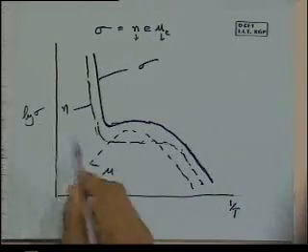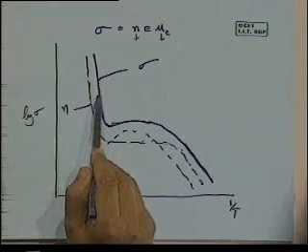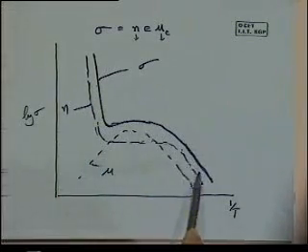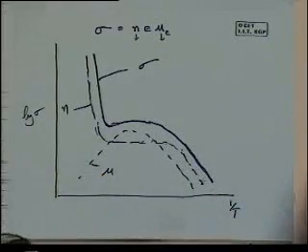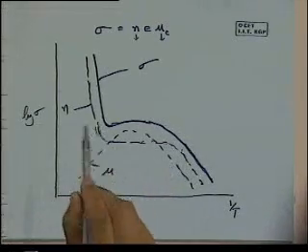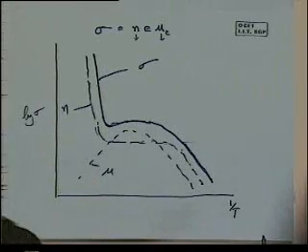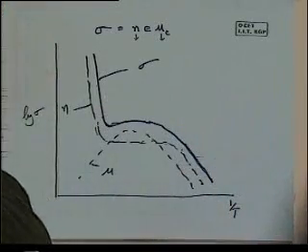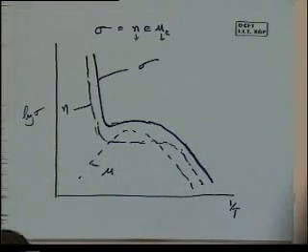The slope of the conductivity curve can roughly be used to get information related to E_g or delta E, because the curve is primarily following the carrier concentration. However, the more accurate value can be obtained from the carrier concentration curve directly. So we've given a picture of how conductivity changes versus 1/T — conductivity increases with increasing temperature.